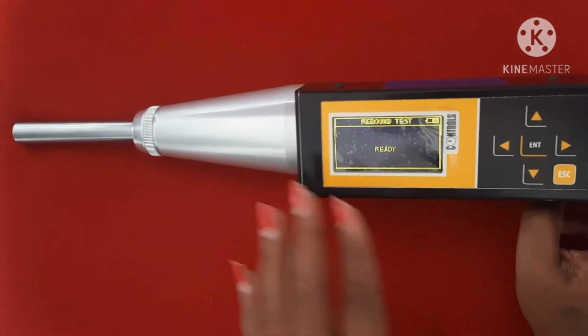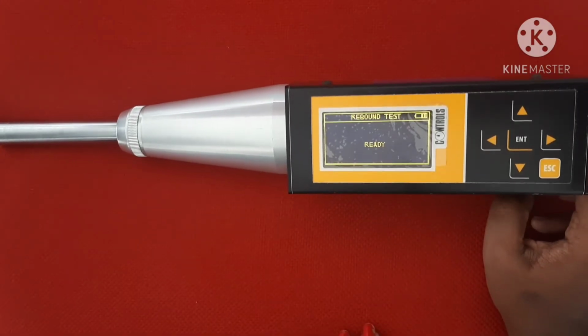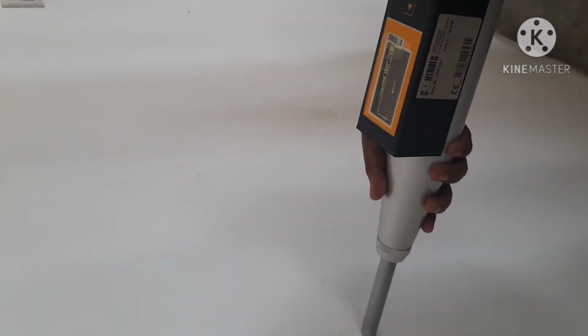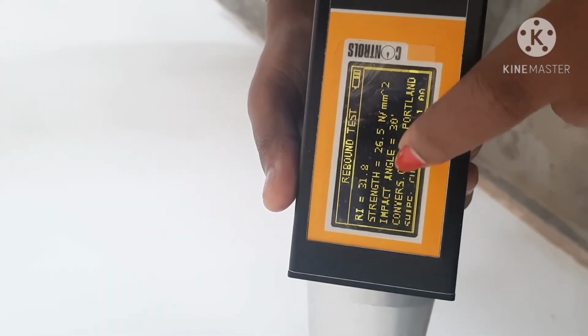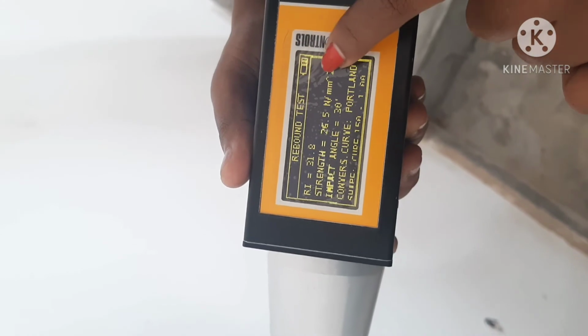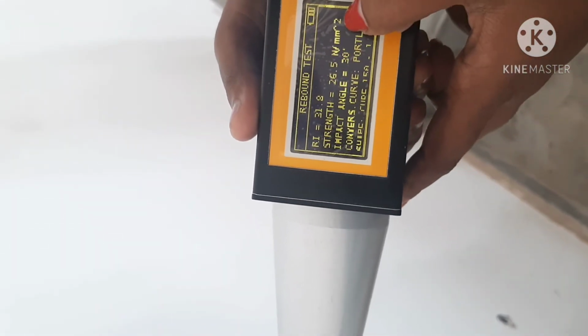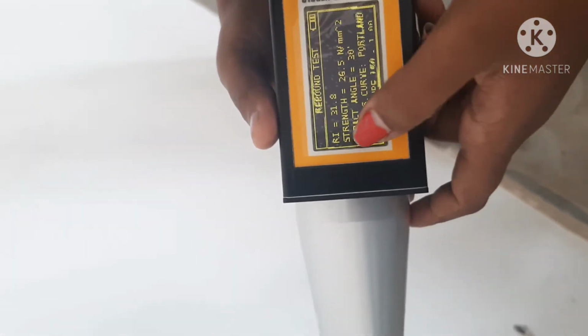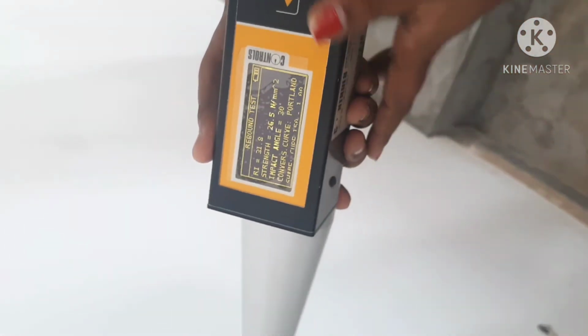We can place it on our plane and check it. Now we are going to demonstrate with a vertical surface. Place the rebound hammer perfectly horizontal and just give a gentle push. At that time we can hear an audible sound. Now our rebound test is done and we are able to see the test results. The rebound index is 31.8 and the compressive strength is expressed in Newton per millimeter square. Likewise, we can test vertically upward or downward, perfectly horizontal, or at any angle as we wish.